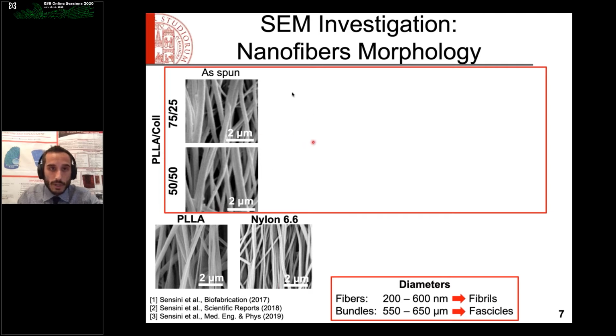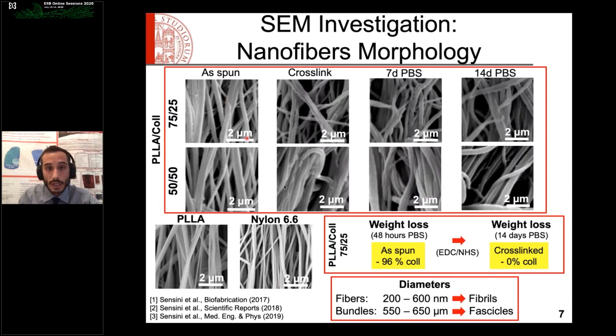Moreover, in collaboration with Dr. Chiara Gualandi, we designed and optimized a dedicated cross-linking process for our PLA and collagen nanofibers, because after cross-linking, the collagen lost its triple helix configuration and becomes soluble in watery environments. So we optimized this cross-linking process using EDC and NHS, which allows us to maintain the shape and morphology of the nanofibers even after 7 and 14 days in physiological environment.